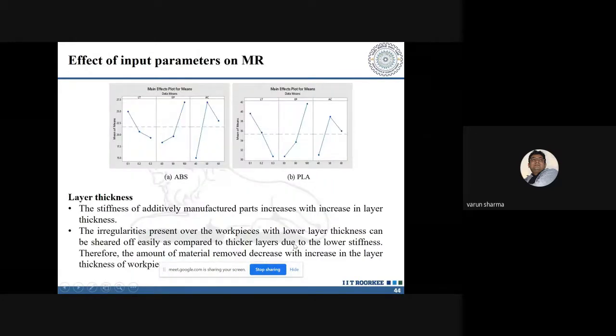So the effect of these input parameters on the material removal rate: what you could see from here is that similar kinds of trends have been achieved for the ABS as well as for the PLA work material. Now, in the case of the ABS, what we found is that as the layer thickness increased, the material removal decreased. This is generally because the stiffness of the additively manufactured part increased with the layer thickness. So as your layer thickness increases, the material becomes more rigid. Fine. Now, as the material becomes more rigid, the material removal decreases in a similar manner.